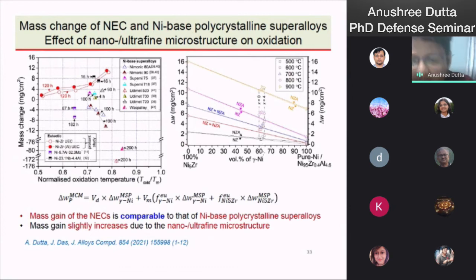In the mixture of phases, gamma nickel volume percent in the NEC is present in the form of either gamma nickel dendritic phase or gamma nickel lamellar eutectic phase. So the total volume percentage of gamma nickel is about 60%. The mixture of the phases should follow this line. But the oxidation of the NEC is actually somewhat higher than this because of the presence of the ultrafine microstructure. This ultrafine microstructure causes a faster diffusion path of the cations and increases the oxidation slightly.